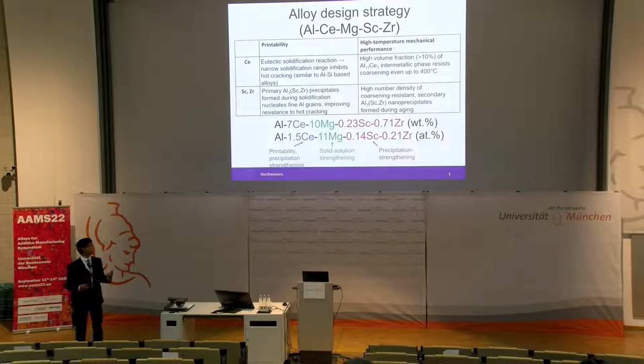Scandium and zirconium are also quite popular for reasons that others have mentioned today and yesterday. This is due to the effective grain refinement from these aluminum-scandium and aluminum-zirconium precipitates, improving resistance to hot cracking, and the formation of coarsening-resistant nano-precipitates. So the idea behind this alloy is that we combine cerium, scandium, and zirconium with additional magnesium for solid solution strengthening, providing an alloy of excellent printability and high temperature performance.